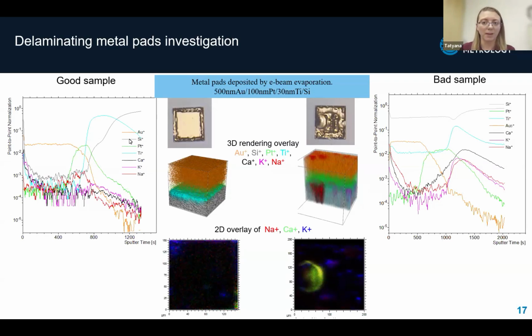even on the optical image they can see something is wrong, but to understand why they need to analyze it in depth. The depth profile reveals a lot of mixing between layers, especially in the middle region. This is even more obvious in the 3D reconstruction. Instead of clean layer boundaries, we see significant interpenetration within metals.